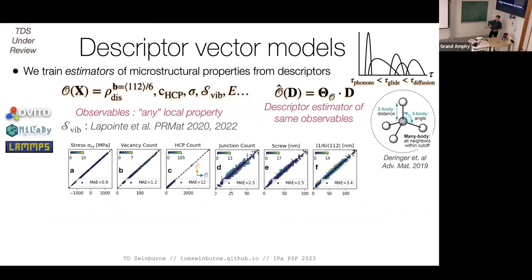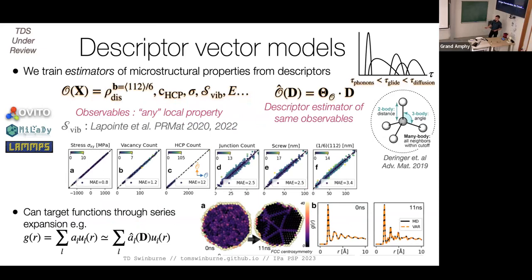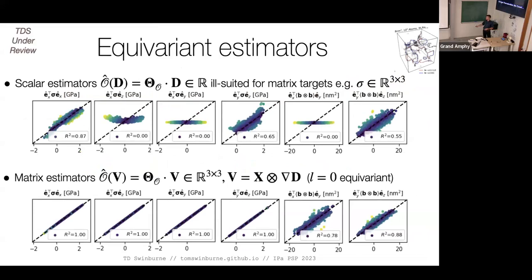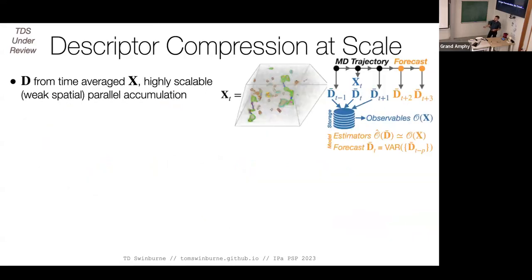I can look at scalar properties and even correlation functions by learning the scalar coefficients of a series expansion. I can produce radial correlation functions, predict numbers of dislocation junctions — quite obscure properties. This 200-dimensional metric space is sensitive to all these properties across a wide range of simulations. I can produce matrix-valued properties as well as scalar-valued ones. This is a medium-dimensional metric representation sensitive to the properties I might want, and the idea is that working in this space, I can predict the future of some time series based on learned data.